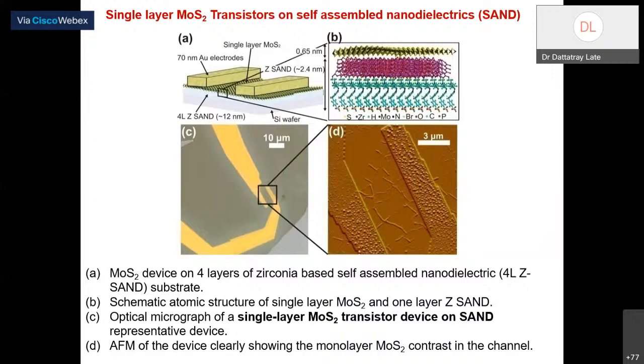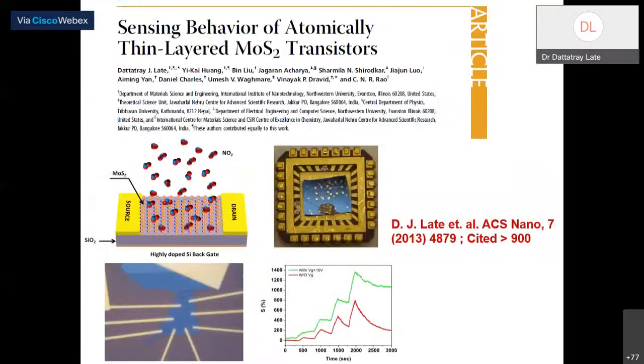The SAND gate is nothing but a combination of a lot of these materials, for example sulfur, zirconium, hydrogen. The combination of these materials, with this particular thickness, we have used as a SAND gate, or this is a gate electrode. And we have kept a single layer of MoS2 on this particular SAND layer having a thickness of 2.4 nanometers, and we have tested the device performance. So this is a very simple thing, and we found that they can be efficiently used. I have used this same material again for field effect transistor applications as well as a transistor-based sensor.